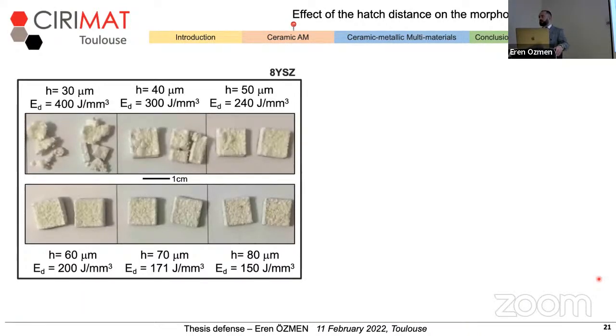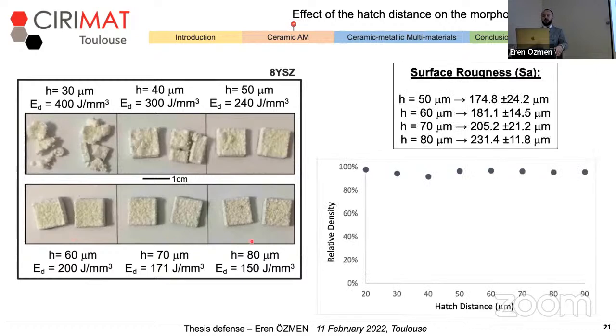The next effect was checking the hatch distance. For 8YSZ pieces, except 50, which was kept stable during process optimization, hatch distances 60, 70, and 80 were also working. The most significant change was observed in the surface roughness. We see that surface roughness is increasing with increasing hatch distance. The relative density of pieces remained stable with increasing hatch distance.